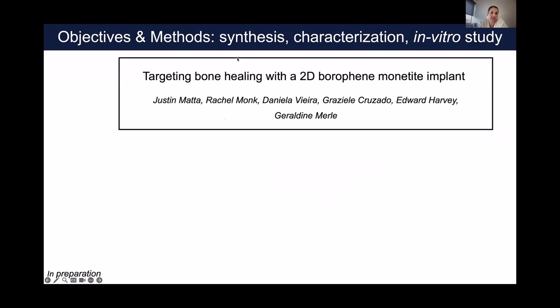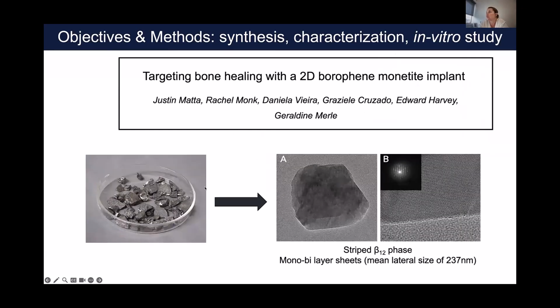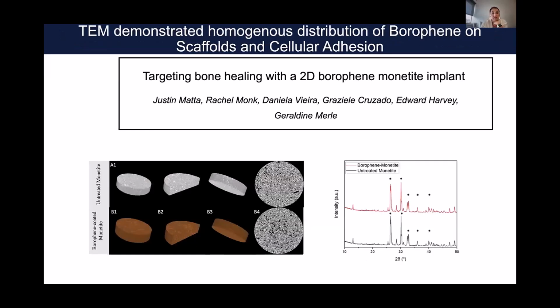And this is the work of Justin Mata, who should be graduating before the end of the year. He spent a huge amount of time trying to exfoliate borophene from a boron nanoparticle. And that was a pretty difficult job, because what you want is a very big lateral dimension with just 1 or 2 layers of borophene. And at the end, he did it by playing with solvent and ultrasound parameters, and he was able to mix those borophene nanosheets with, again, monetite implants.